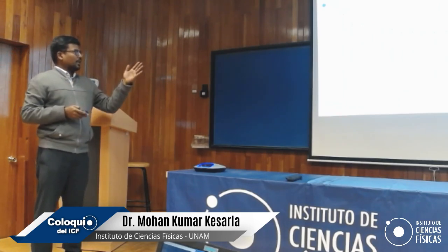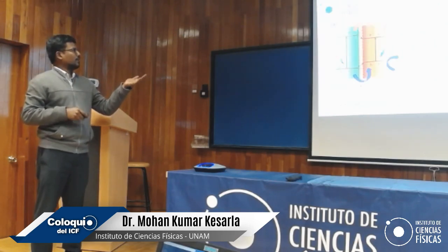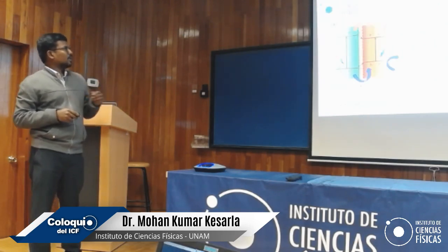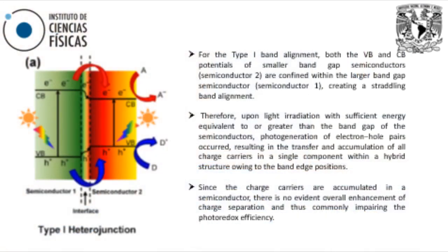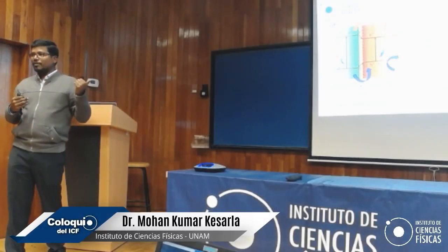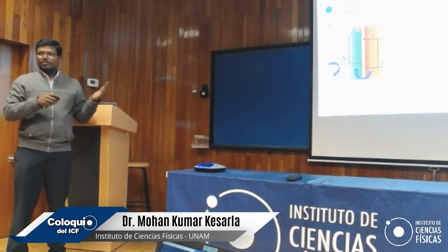So keeping this in mind, we start with the type 1 alignment. What happens in type 1 alignment? There is charge transfer from the higher conduction band to the lower conduction band, and from the higher valence band to the lower valence band. But the problem is, upon irradiation of this type of heterojunction, the photogenerated electron-hole pairs result in the transfer and accumulation of charge carriers in a single component within the hybrid structure, and there is no evidence of good control on charge separation in this type of heterojunction. So people always believe in the second one, the type 2 heterojunction.